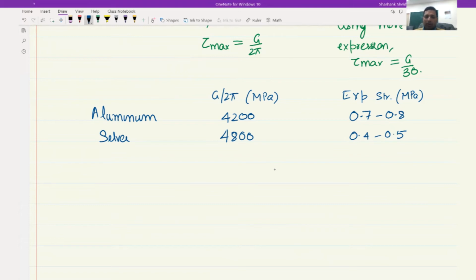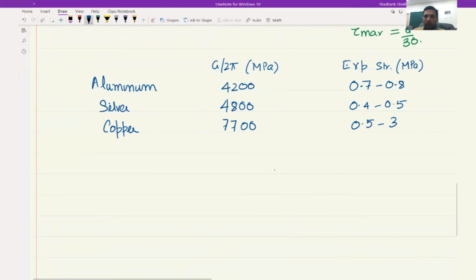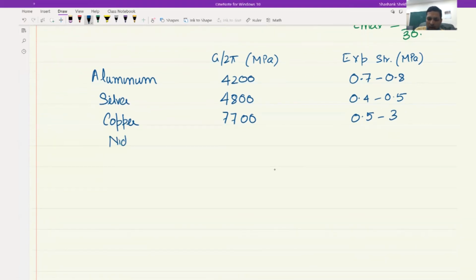So which assumption is wrong? Most likely that is not how the deformation is taking place. This is not how the material is deforming. So just to further emphasize that, let me put some more examples here. Copper, 7700 should be the theoretical strength, and what we get is 0.5 to 3. Even if you go for nickel, which has much higher experimental strength, which is of the order of 3 to 5, but theoretical strength is even higher,